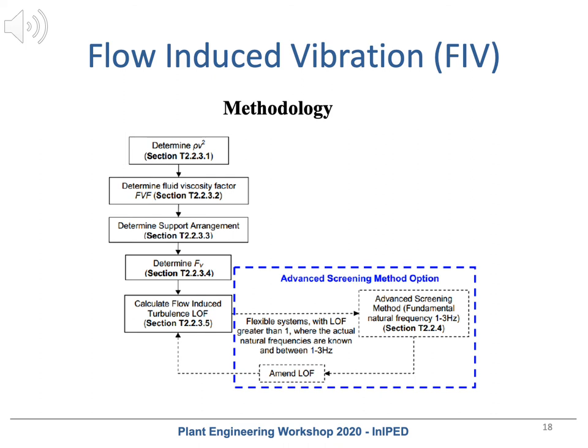Second stage: a standard assessment using the Energy Institute guidelines for lines which have failed the preliminary screening process. For these lines, it is necessary to carry out a detailed calculation of the probability of failure. For this, in addition to the data of speed and density, the dynamic viscosity is needed for the lines whose flow is in a gaseous state, and the geometric characteristics of the line, such as the outer diameter and the thickness of the pipe. The probability of failure is calculated as shown on the attached picture.